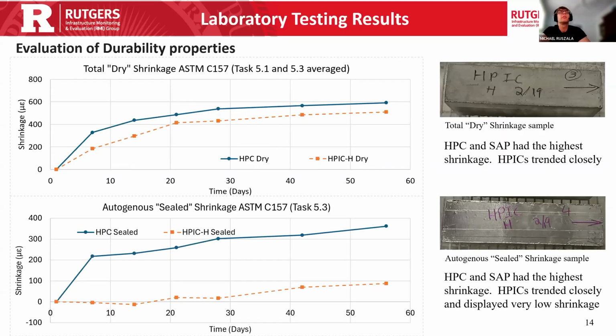So regarding shrinkage, which is kind of the whole purpose of this, to reduce shrinkage and to reduce the cracking potential. With dry shrinkage, we typically saw less of a reduction, maybe more at early ages. But with the reduction in autogenous shrinkage is where these materials really do shine. You can see that for the early ages, autogenous shrinkage was highly reduced. And this allows the concrete to gain strength before these forces develop in these restrained conditions that lead to the cracking that we're trying to avoid.